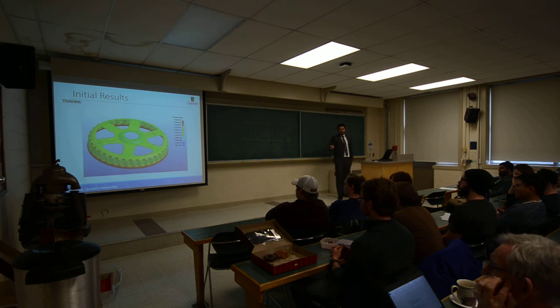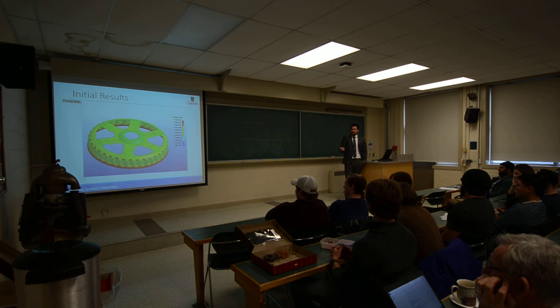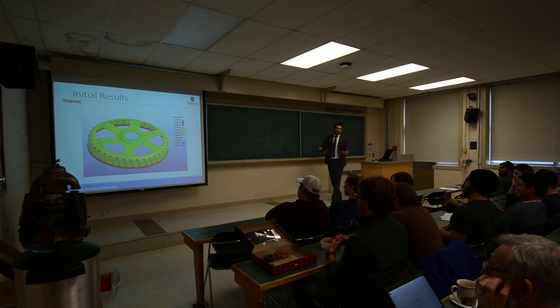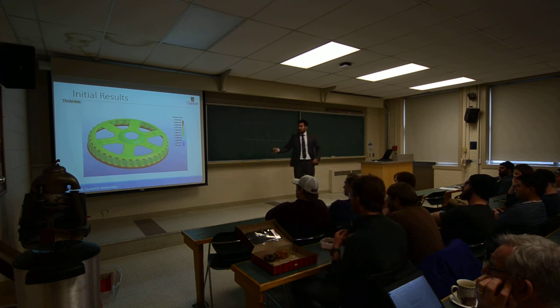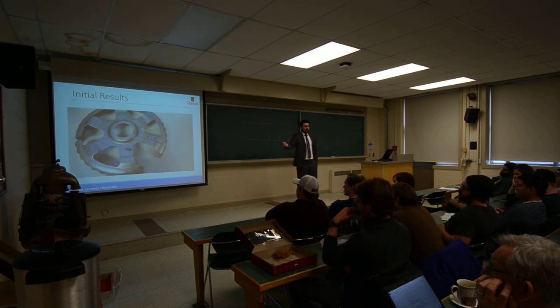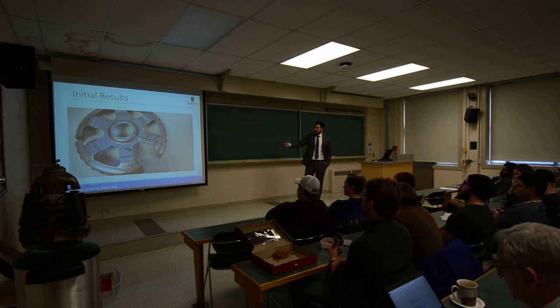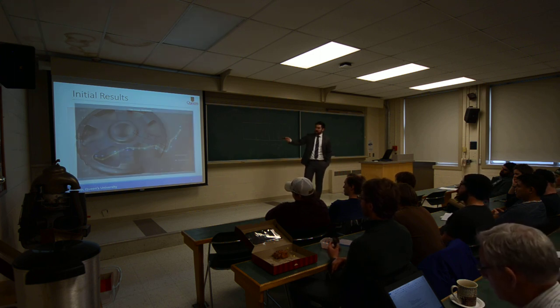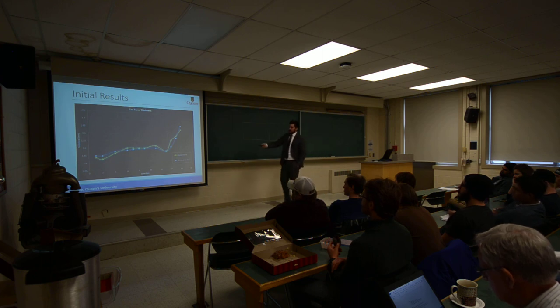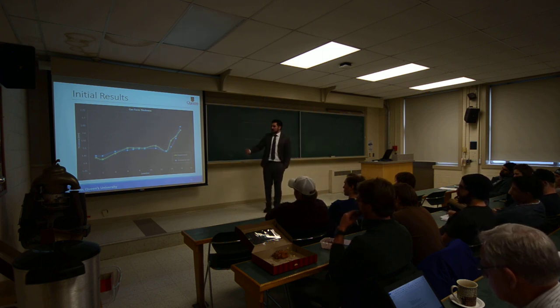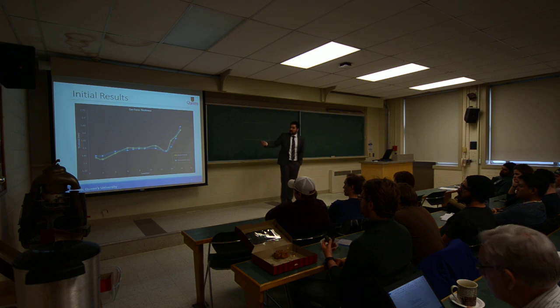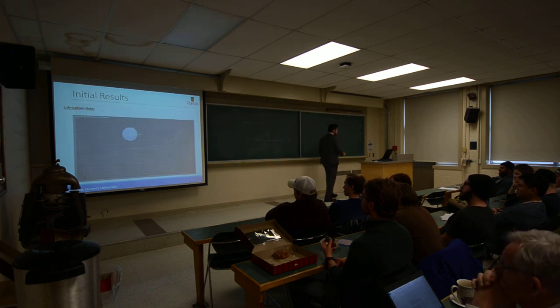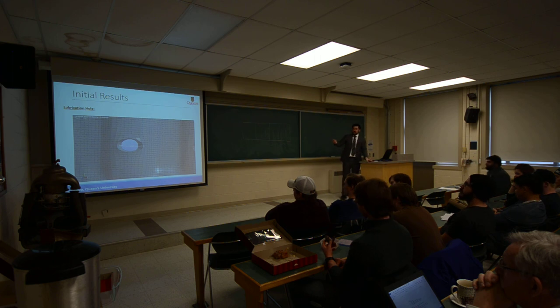Another result we can examine is thickness distribution, which is a good way to validate the mechanical side of the model. As the part is formed and stretched, we see local bunching and thinning in certain areas. We can take a physical part that has been stamped in reality, define measurement locations, correlate those with elements in the simulation, and compare the thickness distributions between the experimental and numerical models. We see quite good agreement — note the scale is small, covering about 4 millimeters from top to bottom.